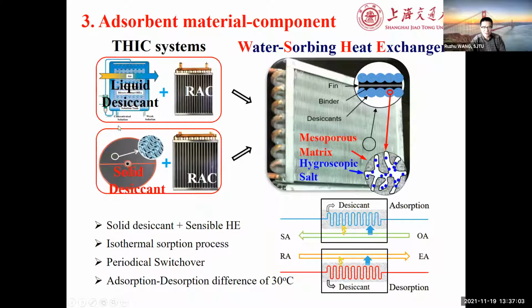And what's important is that we try to use this for a temperature and humidity independent control system, because for air conditioning, you have liquid desiccant with sensible heat exchangers for dehumidification and cooling, or using desiccant wheel dehumidification and the sensible heat exchanger for cooling. In this case, versus a normal evaporation air conditioning system, you could get an evaporation temperature of more than 15 degrees centigrade, because dehumidification is done by the liquid or solid desiccant. But now we have this kind of desiccant coated on the heat exchanger. So this will be a water absorbing heat exchanger.